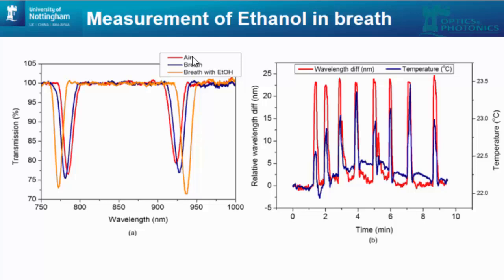You can see also the temperature response here. So this difference between the red and blue line is only the effect of the temperature. By subtracting this, you can actually tell that you have ethanol present in breath. So it's a very simple proof of concept, but we can use different materials that will be selectively sensitive to other compounds, and in healthcare applications, this is quite convenient when you want to measure some biomarkers present in breath. So this is a preliminary focus of our work, but to demonstrate the proof of concept.